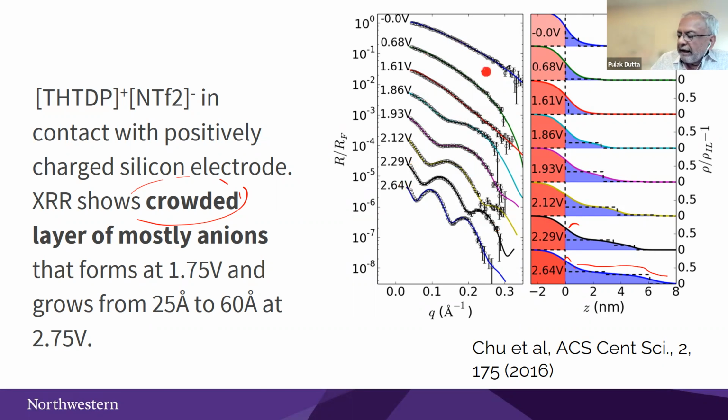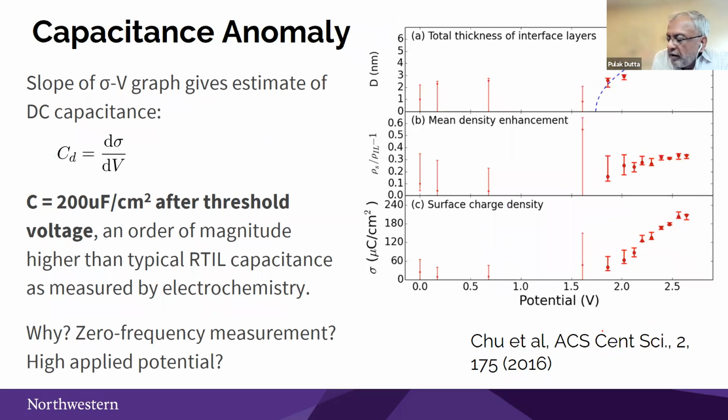Okay, here, if we went to higher Q, presumably there would be that minimum we saw in the Metzger et al. paper, but we were interested in the low Q data. And you can analyze the data to get the thickness. Here's the thickness as a function of voltage. There seems to be a threshold. Okay, if you extrapolate it back, there seems to be a threshold. You can basically take this and ask what the density is as a fraction of the bulk IL density.